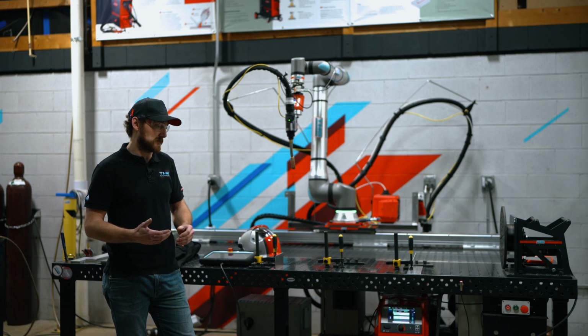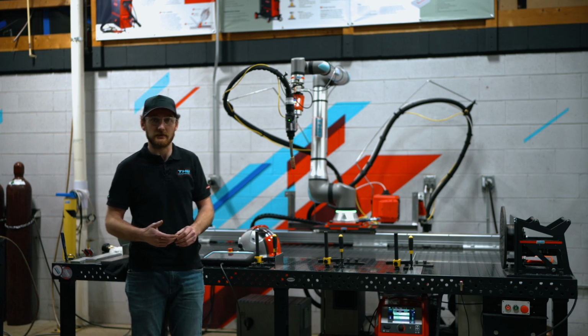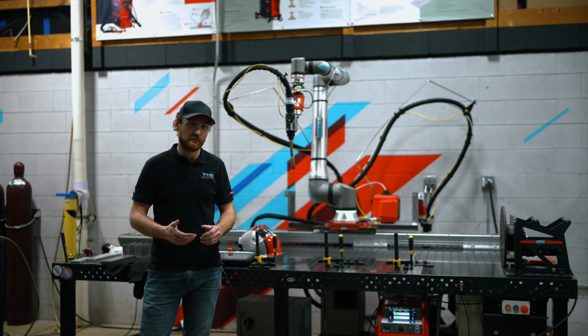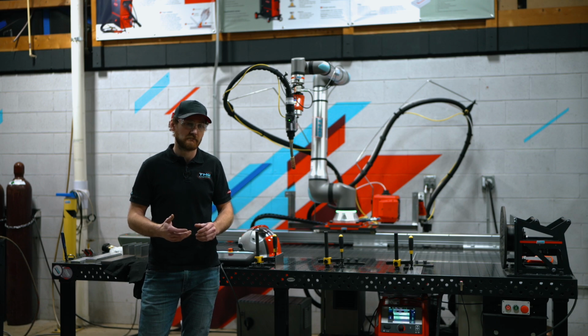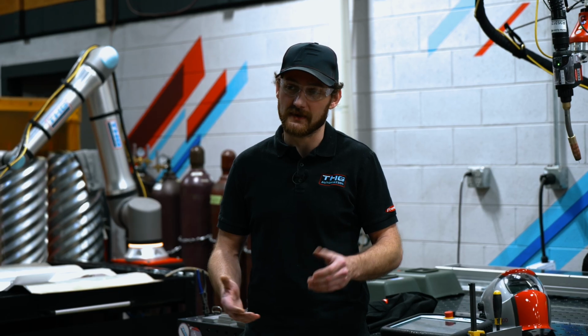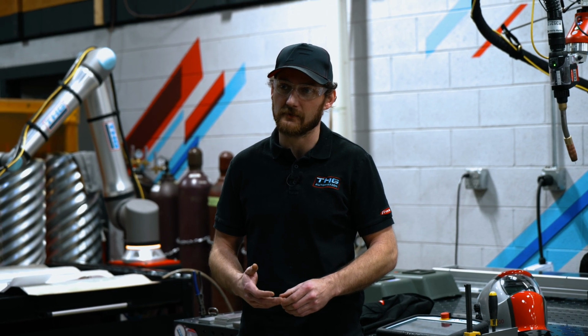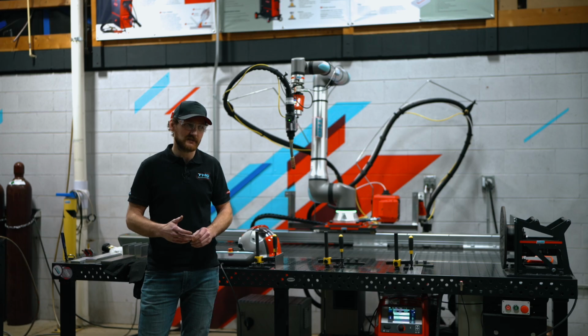We also have PMC, CMT, and also the mix processes that go along with those, and ripple drive. You have the AC capability, so it kind of can help with thinner materials and gap bridging, or you can go with, say, a standard universal or a PMC dynamic and get kind of the punch for thicker aluminum materials. CMT is kind of a cooler process, kind of helps more with the thin materials.